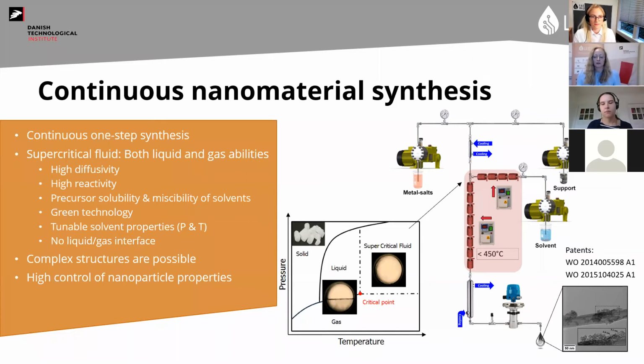And the smart thing here is that when this supercritical fluid hits the cold stream of reactants, it will form very small particles very rapidly that will then flow through the reactor and be matured through the second heating part, cool down rapidly, and then be collected. And one of the advantages here is that by just changing the pressure or the temperature, we move around in the supercritical phase area in the diagram. So maybe we could be just near the edge between the liquid and the supercritical phase. And here we can actually tune the particle size or the particle properties. So for example, if we change the pressure and temperature, we'll get a smaller particle size compared to if we have other pressure and temperature. So it's quite easy to adjust.